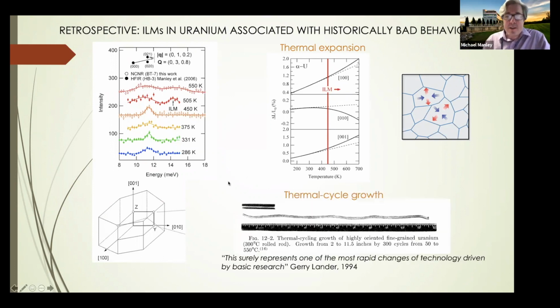And there's quite an amazing picture here. This is a piece of thermally cycled growth of a highly oriented uranium grain. It grows from 2 inches to 11.5 inches after 300 cycles from 50 to 550 C. So this stuff just basically tears itself apart. And you can see this.